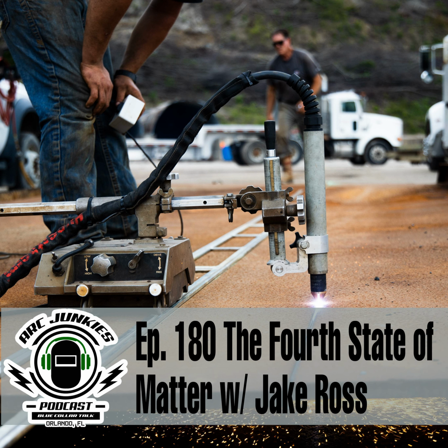Yeah, absolutely. So flush cut is a very unique process. We're bending the arc at a 45-degree angle, and then we also have a drag shield on the bottom that's chamfered at a 45. So imagine that you're cutting out a lifting eye. You're shooting the plasma arc out parallel to the base material. And the advantage to that is I'm not damaging the base material. I mean, even with running scarfing tips, it's pretty easy to damage the base material.